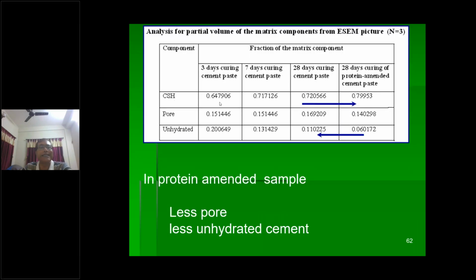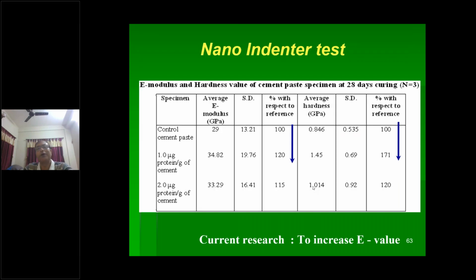From the analysis of the matrix at 28 days, comparing the normal cement paste and the protein amended cement paste, we get a higher CSH gel quantity, lower pore quantity, and less unhydrated part in the protein amended sample. So we get the advantage in the protein amended sample of less pore and less unhydrated cement. We have also done a nanoindentation test to check whether the E value changes or not.